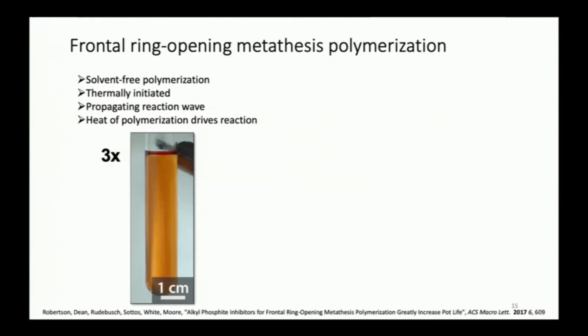First, let's talk a little bit about some interesting chemistry that I think is quite suitable for manufacturing in the wild. This is a bulk polymerization. It's taken from the very beautiful work that's come out of the Grubbs lab over the last couple of decades, using dicyclopentadiene, a readily available feedstock that's currently burned as jet fuel, to polymerize that in a very controlled way by a bulk polymerization, a solvent-free polymerization, where in terms of energy efficiency, and Susanna did a very nice job of going through that energy efficiency process that typically is used to make polymeric materials.